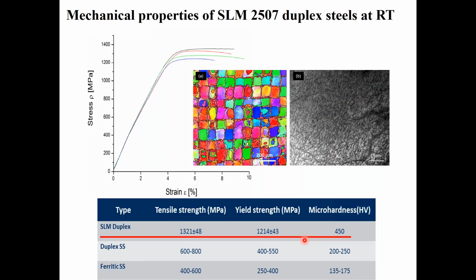So this is the second steel, duplex 2507, and this is the as-built sample. And interestingly, after SLM, it is only ferritic instead of duplex. And as produced, we get a tensile strength of 1321 megapascal, yield strength 1214, and hardness of 450, which is comparatively very high for duplex stainless steels and also ferritic stainless steel.